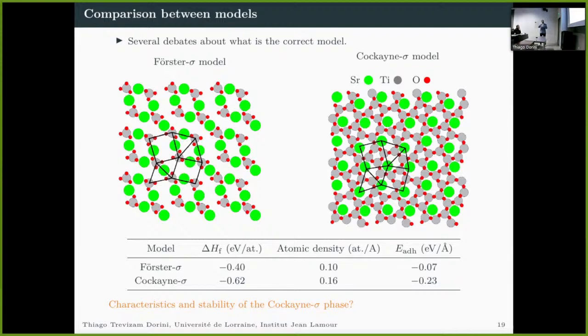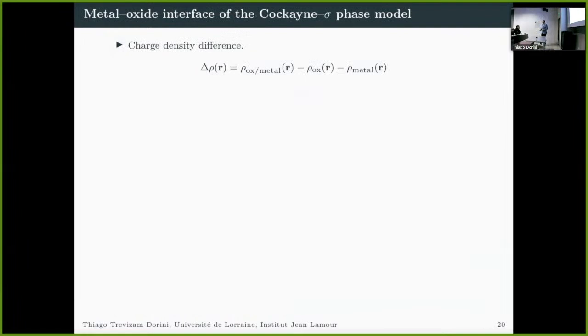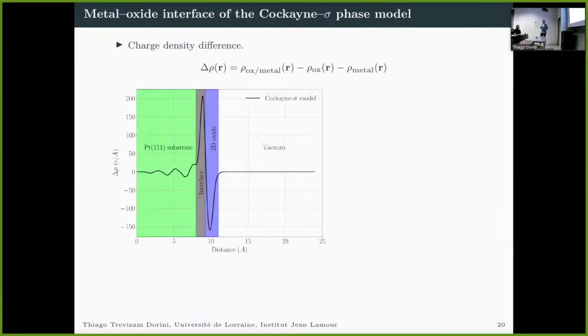So now what we would like to do is use this model to understand their characteristics, specifically at the interface between this oxide and the platinum substrate, and the stability of this phase. And I'd like to start with a very general property, which is the charge density difference. In this case, what we can see in blue, we have the charge density difference in the oxides, and we see that the oxide is actually donating the charge, especially to the interface region and to the first layer of platinum.